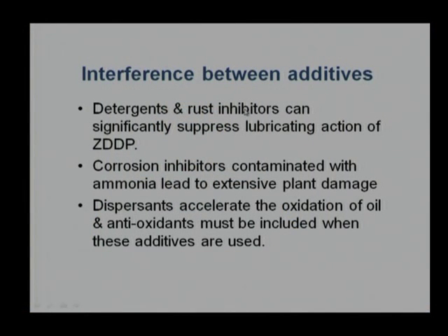That means when we are doing a coating of solid lubricant on the surfaces, then we don't really require additional rust inhibitors, if you know that kind of solid lubricant will remain there for a long service life. But if there are some detergent and rust inhibitors, then we need to be very careful about physical attachment or chemical attachment of additive to the surface, because detergent and rust inhibitors will try to separate anti-wear additives from the surface.